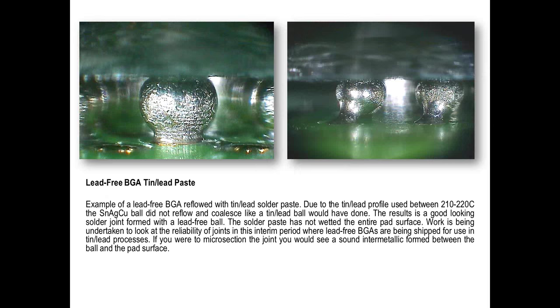When you're mixing tin, lead and lead free is something you should avoid. And generally speaking, it's not an issue today because most people are using lead free and lead free BGAs. There is great debate in the industry about if you mix them together, the solder joint reliability is not as good. And there's been mixed studies on this, both positive and negative. It just depends when you started and when you ended in this conversation.